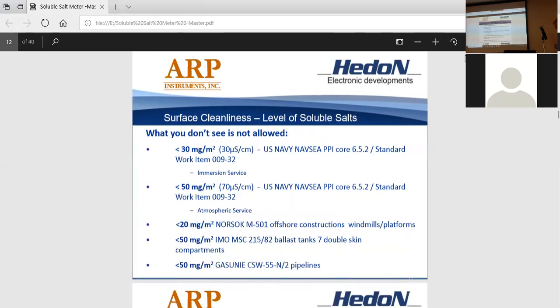That was determined by a number of studies to look at where I see blistering with the degree of contamination, where my risk factors are. And then we did tons of fleet installations and tracked them. By controlling those levels, we saw a tripling, quadrupling of the service life in our tanks and underwater hull by controlling the soluble salts. It was a great investment. And at the same time, we went to high performance coatings, high solid coatings.